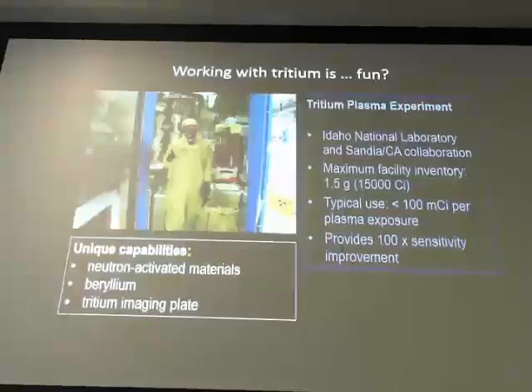Oh, okay, yeah, it's definitely very small in comparison to that. The fluxes that we can get in here are about a factor of 10 less than what would be possible to obtain, what would be expected in ITER, for example. And ITER would be, so that we can run for longer time, so we can get higher fluences as a result. An ITER shot would be 400 seconds or so. We can run this for hours and hours.